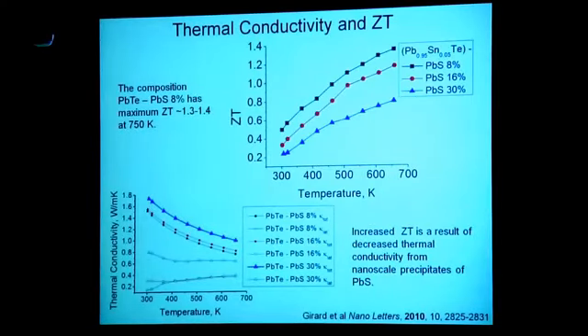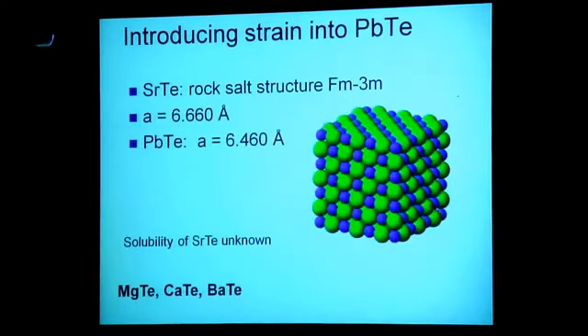So then you can take that and you can do doping. Here we did N-type doping using lead chloride. The chloride substitutes the telluride in the lattice. It has one extra electron. It makes it N-type. And then we were able to optimize the power factor with different doping levels. And using the very low thermal conductivities here, we were able to get ZTs of about 1.4 or so at high temperatures. So this is a great thermoelectric system.